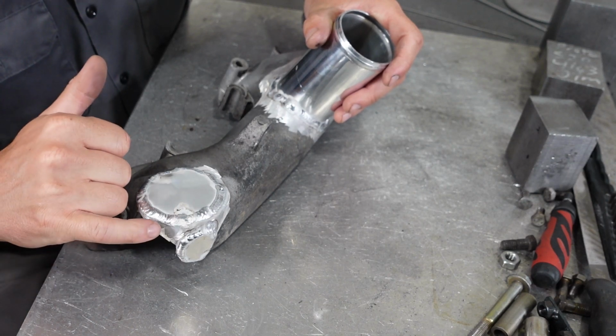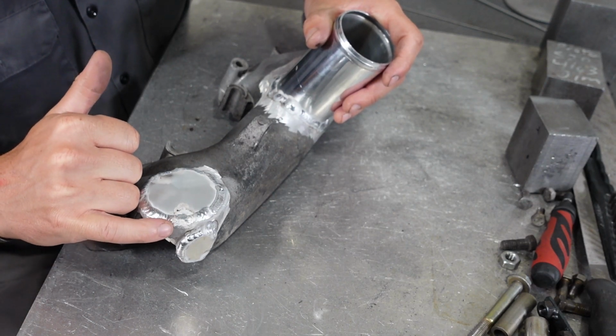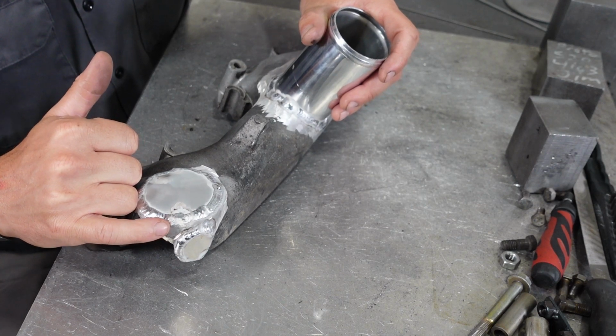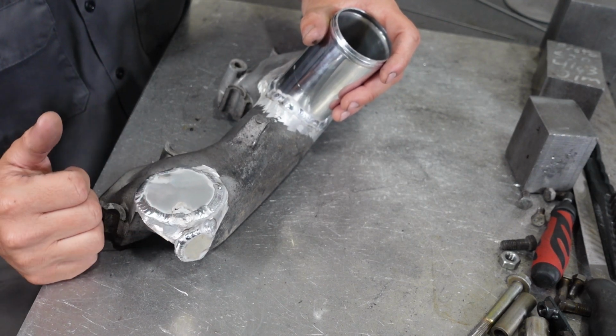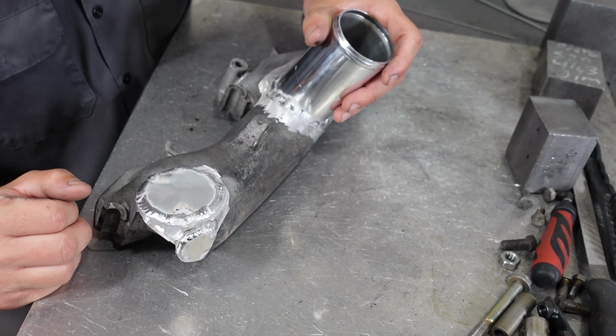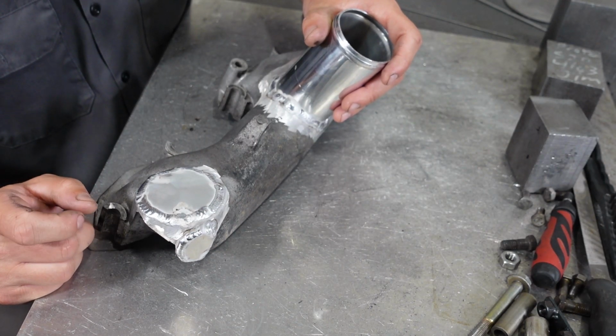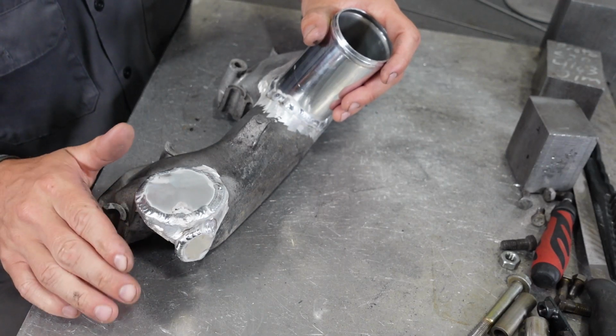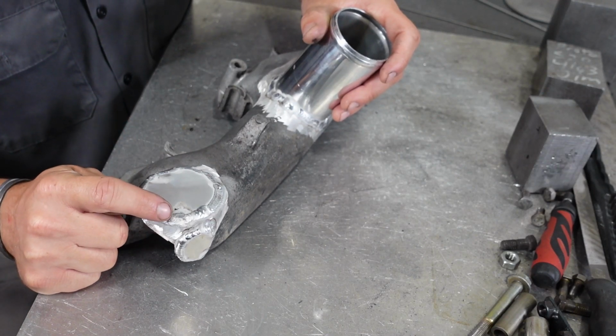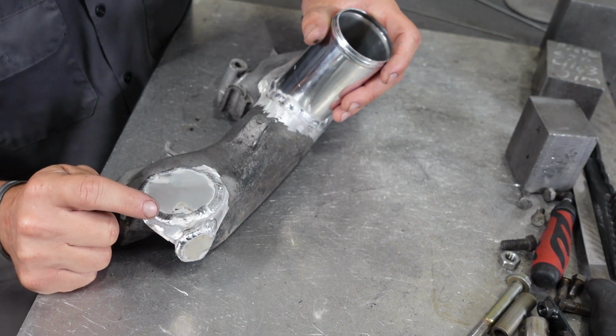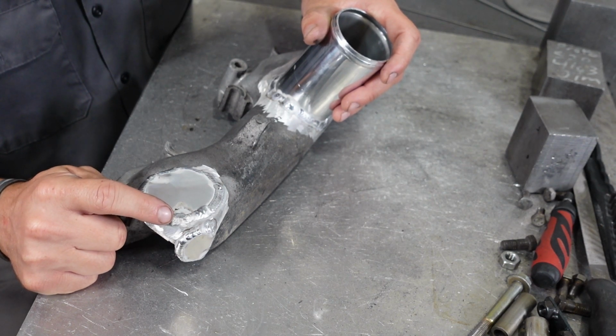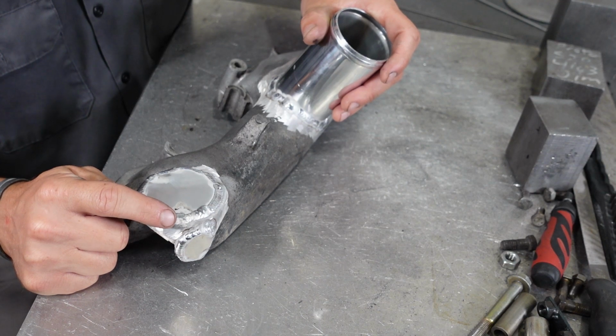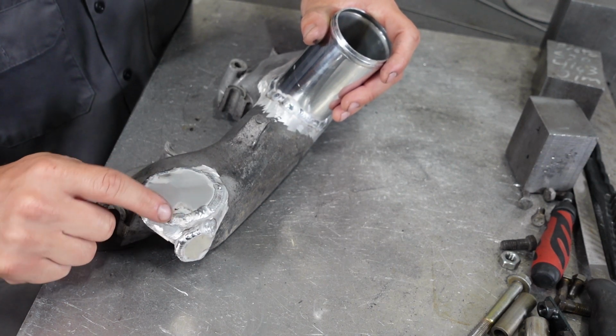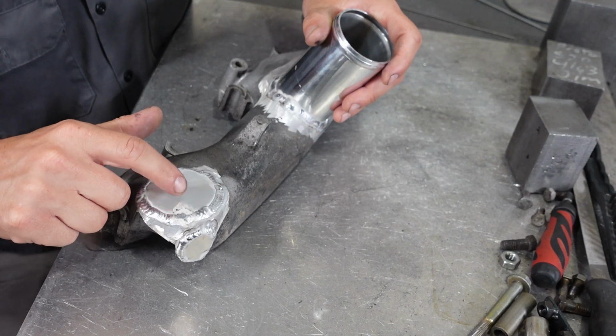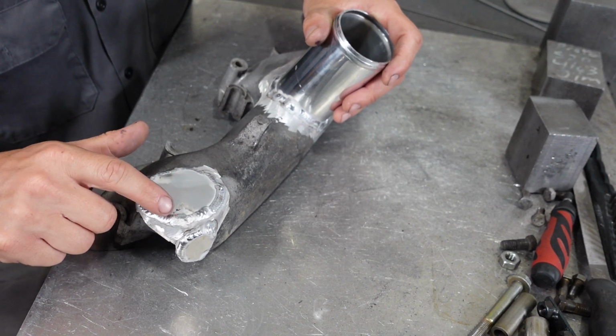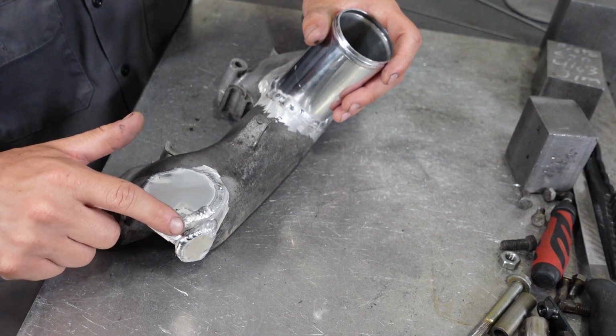You will see a million little holes pop up, and don't freak out, but don't try to sit there and zap them and melt it all to get it to go away, because that's just going to make it worse. You're going to have even more holes. You have to let it cool off, come back, get an arc going, get some nice clean filler material to work with, and try to work that area with the porosity towards your clean base metal. And when you let off the arc and you terminate that arc, terminate it over here on the clean base metal, and that'll help minimize the risk for porosity once you finish that weld.